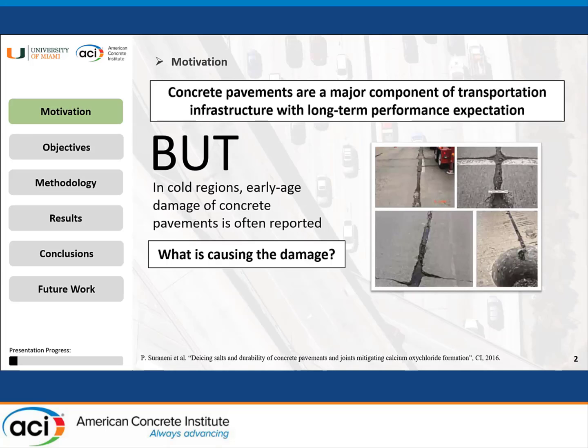So what is causing this damage in our concrete pavements? First, they are attributing this damage to the freeze-thaw cycle. As most of us know, we have temperature variations daily. Usually over the nighttime, the temperature drops below the freezing temperature of water, and over the daytime, the temperature increases. This happens over time, and we have water in our concrete. And what happens when the water in the concrete freezes? It expands, and this expansion causes internal pressure from the inside of our concrete matrix, which can lead to cracks and deterioration of our concrete structure.